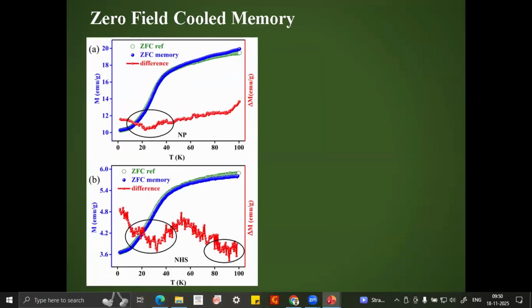On the other hand, the more conclusive measurement is the zero field cool memory. Now, for the zero field cool memory, the green curve is the zero field cool reference curve. After going to 100 Kelvin, we now cool down the system without the application of any magnetic field, that is zero field cool. Without any magnetic field, we go down to 2 Kelvin. Now here, while going down to 2 Kelvin, we also applied two intermittent halts, one at 80 Kelvin, another at 20 Kelvin.